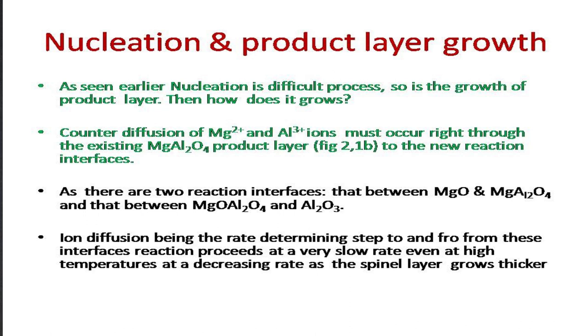Therefore, ions must diffuse, and since diffusion of ions to and fro from these interfaces is the rate determining step, the reaction proceeds at a very slow rate even at high temperature, at a decreasing rate as the spinel layer gets thicker and bigger. So it is the ion diffusion taking place through this layer that is the rate determining step, and that's why it is the slowest step one sees in this particular case.